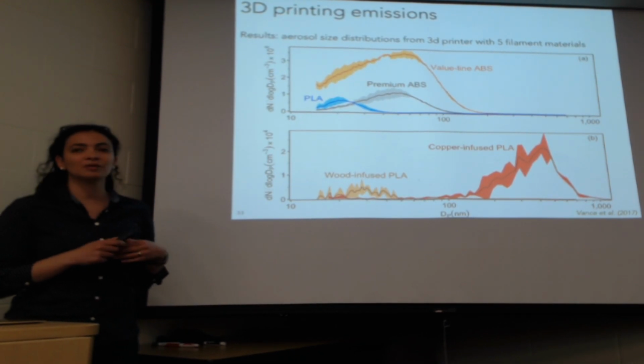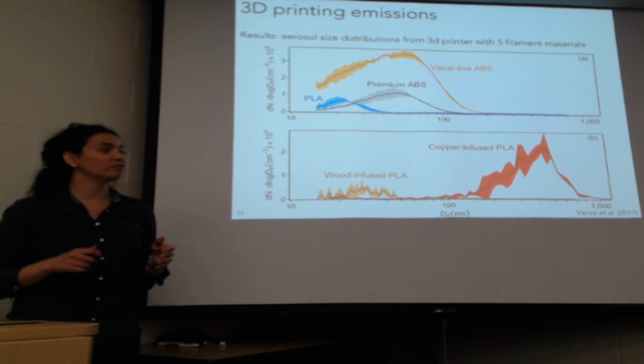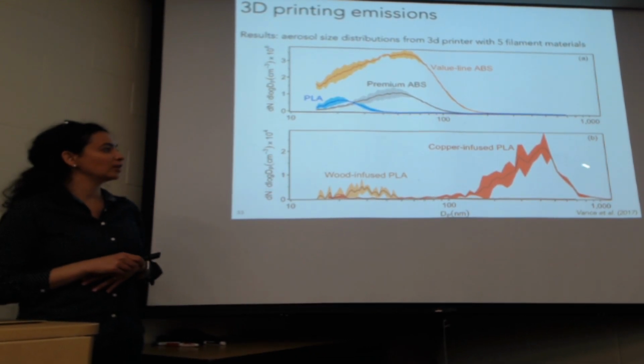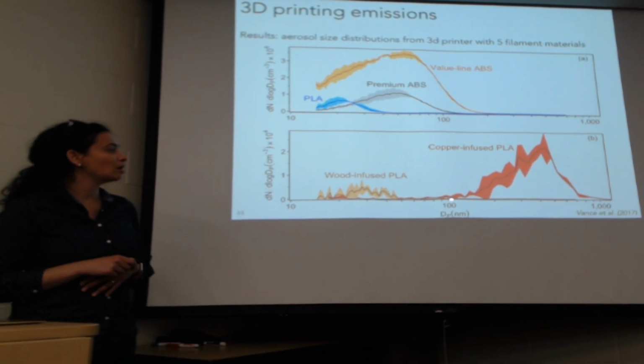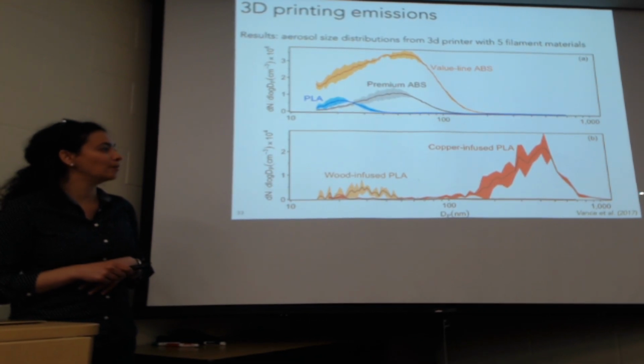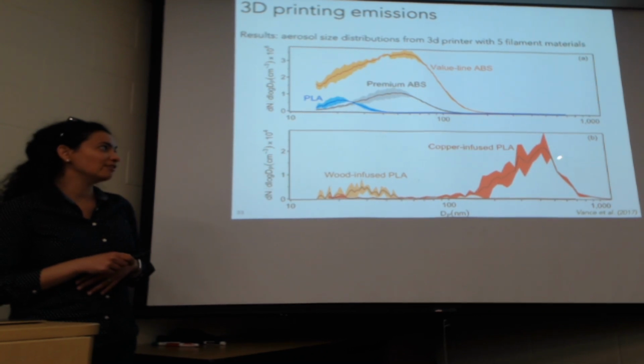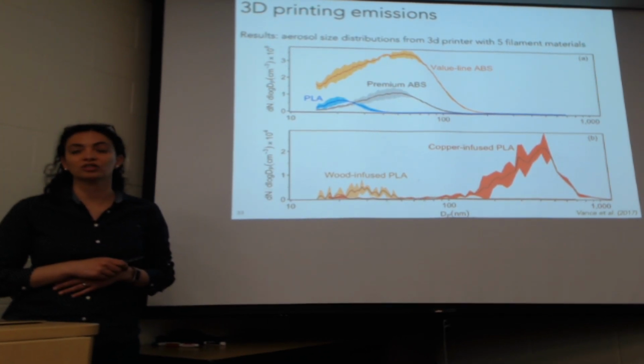But for copper, as I mentioned before, emissions were totally different. For these particles, I had to use a different instrument to get to the size range. These particles were not below 100 nanometers. In fact, they were all above 100 nanometers, and they were about 400 to 500 nanometers in size on average.